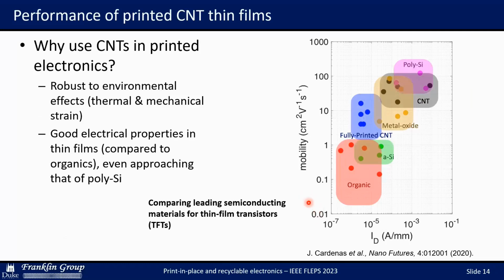So you can see the overall comparative mobility for these types of films, whether it's a fully printed nanotube device, which is in blue, or just a thin film nanotube device, which may have lithographically patterned electrodes in the gray. The mobility of those films, a key metric for thin film devices, competes incredibly well with some of the leading, actually commercial technologies. So polysilicon and metal oxide transistors.